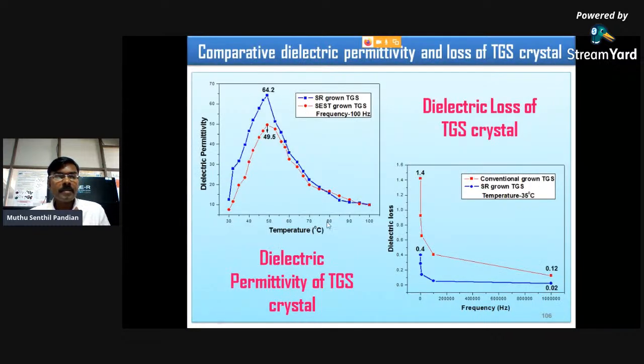So this is the temperature profile of the dielectric permittivity value for the TGS single crystal. When the temperature increases, the dielectric permittivity value also increases, having maximum dielectric permittivity at 49 degrees Celsius. Before this 49 degrees Celsius, this triglycine sulfate crystal belongs to the ferroelectric phase. After this 49 degrees, the crystal belongs to the paraelectric phase.